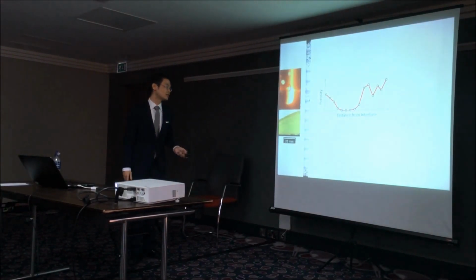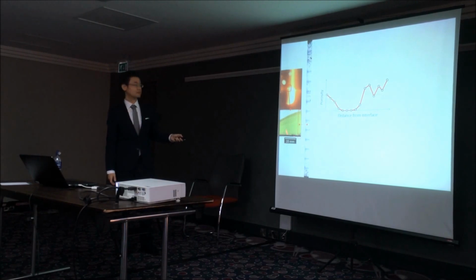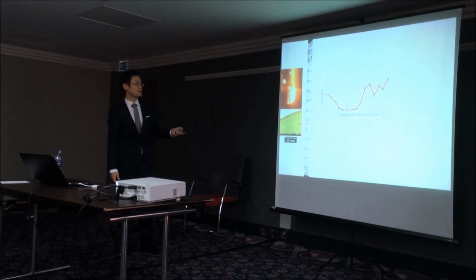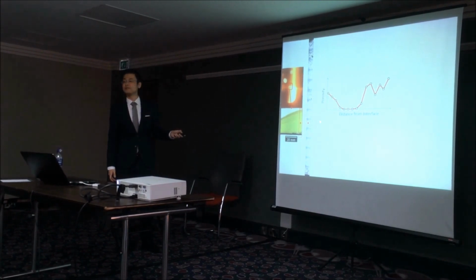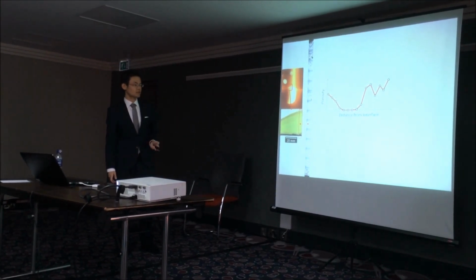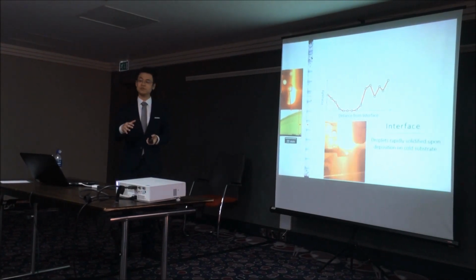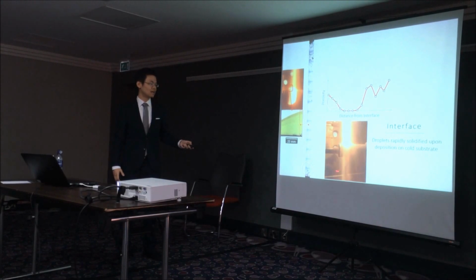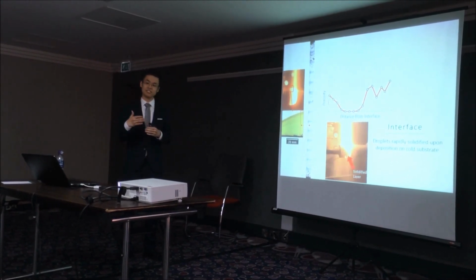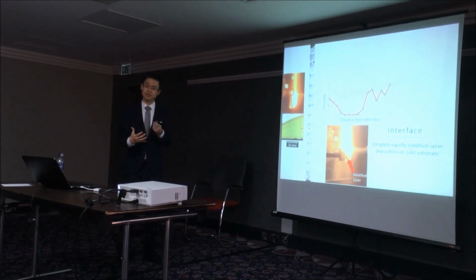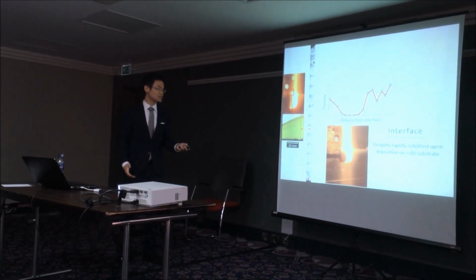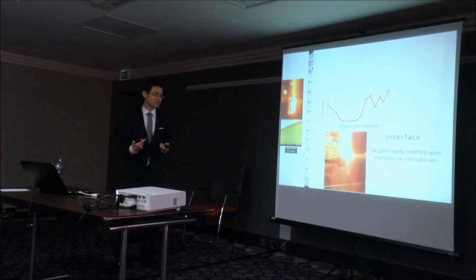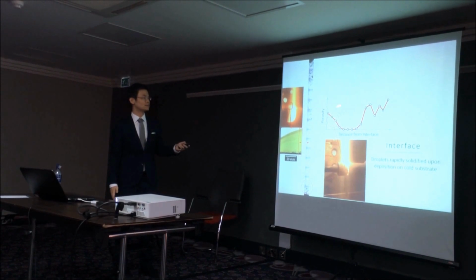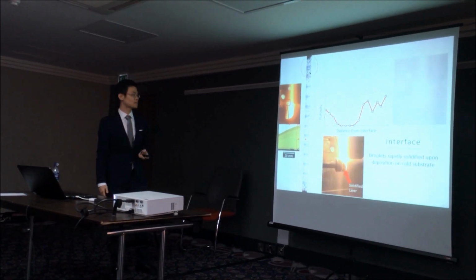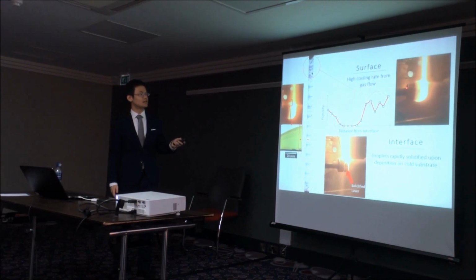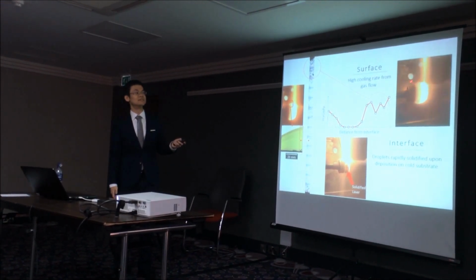Now let's take a look at this in action. So we have a typical cross-section from a sprayed component. And these are the corresponding optical micrographs stitched to show the porosity. At the interface, due to the initial large temperature difference, you can see that we have a solidified layer formed, but it was initially delaminated from the substrate surface. Now as the component's temperature heats up, this solidified layer sticks onto the surface, but it is still relatively cold, forming the porosity at the interface. At the surface, we can see that it is subjected to gas cooling based on the difference in intensity.